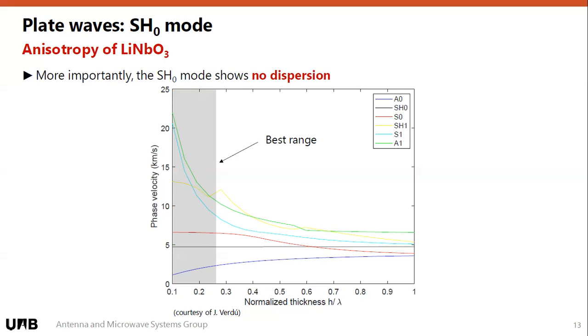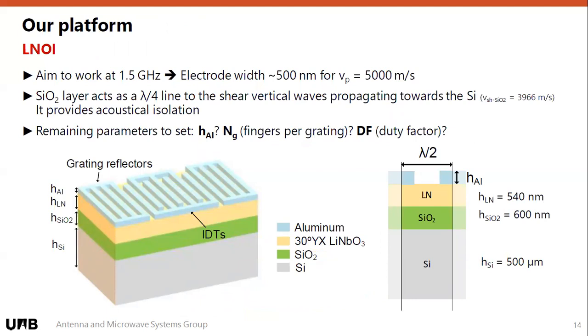this mode showing no dispersion is that we will be worrying about the thickness of our layer, but since SmartCut technologies can assure you, you can buy a layer of 500 nanometers thickness, but then you will have some roughness and some plus minus discrepancy. It doesn't really affect you if your layer is 40 or 20 nanometers away or below your desired thickness. So the frequency at which we start building the resonator is not going to be affected by small deviations in the thickness. So the same structure with the same pitch that we define for the IDT is going to be working precisely if we have these kinds of differences in the layer thickness. So this is a pretty interesting characteristic of this mode.